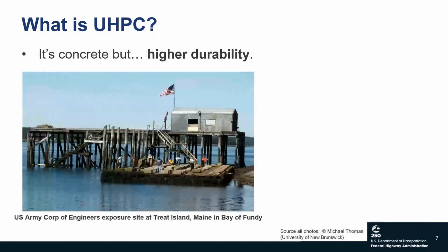But that's not all. Another very important property for UHPC is its high durability. UHPC has a very dense matrix that has a discontinuous pore network. What that means is that it results in a nearly impermeable material, and that prevents water ingress, which protects the integrity of the UHPC itself, but also protects the reinforcement inside from corrosion.